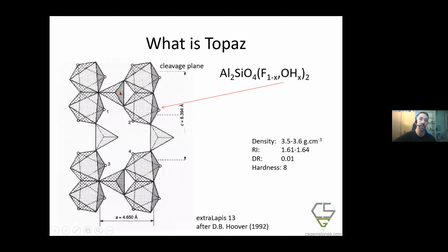So looking at the crystal structure, we have here the tetrahedrons, which have silicon in the core and 4 oxygens at the corners. And we have the octahedrons with aluminum in the core, with 4 oxygens at the corners and two corner points where we can have either the hydroxyl or the fluoride ion. 2 of the octahedrons are connected to each other via one edge. And from the points, we have the connection to the silicon tetrahedrons, and those are building up these 3-dimensional structures. So we have the C-axis going from the top to the bottom. We're looking here in the direction of the B-axis.